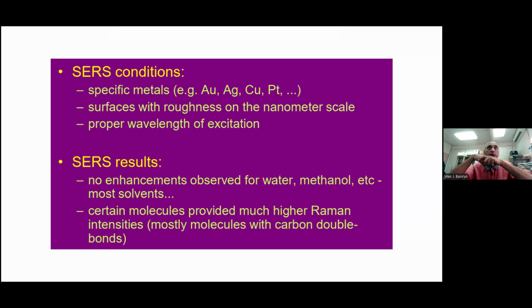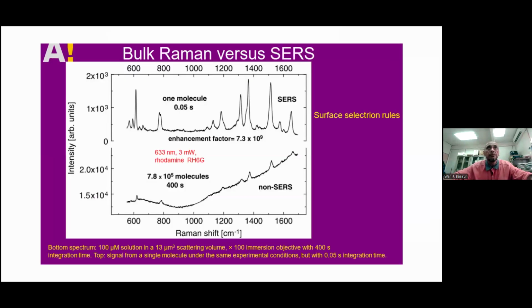And you have SERS when the molecule or the functional group is adsorbed onto a certain metal, for example gold, silver, or platinum, and so on. So that is the condition of SERS. So for example, we look at this example, rhodamine. Rhodamine is an organic molecule. So you look at the enhancement factor.